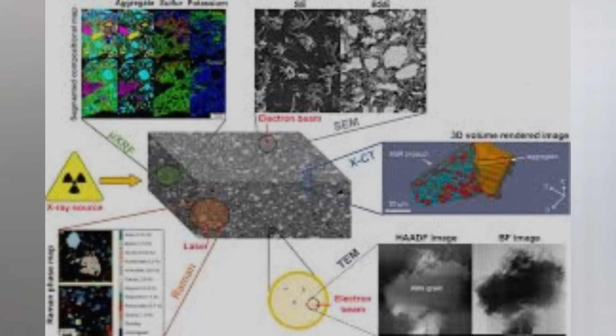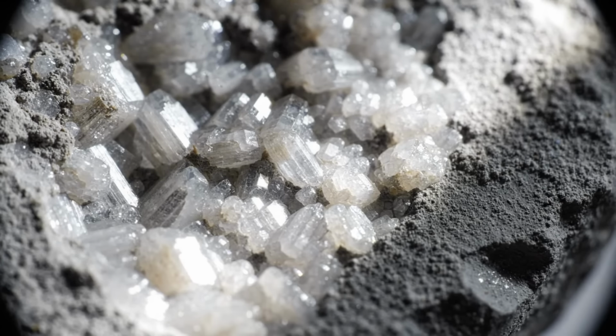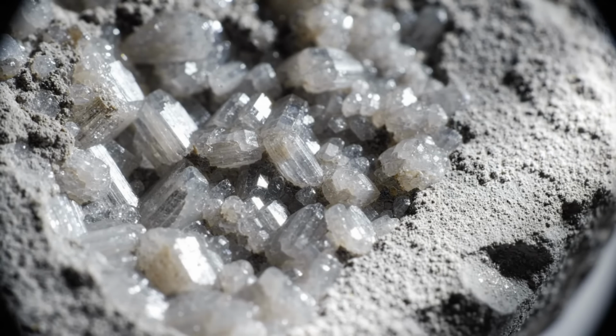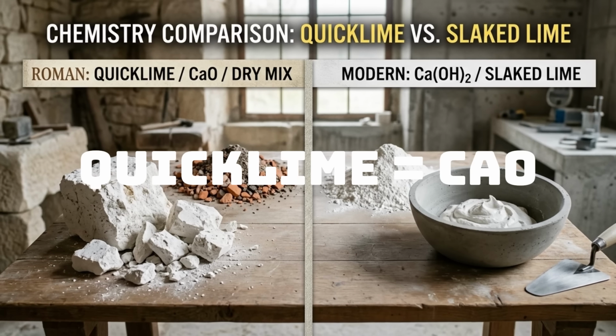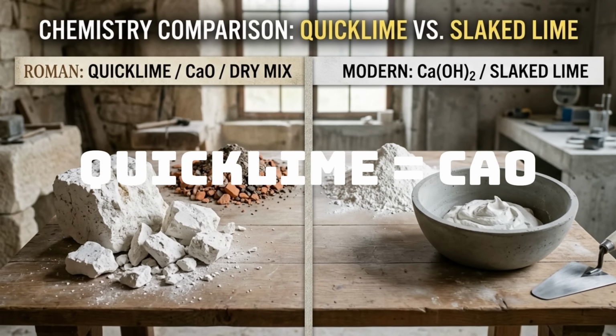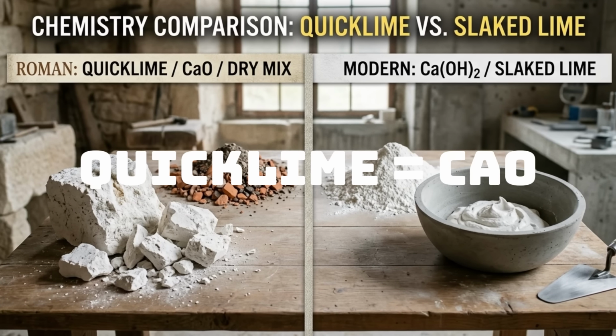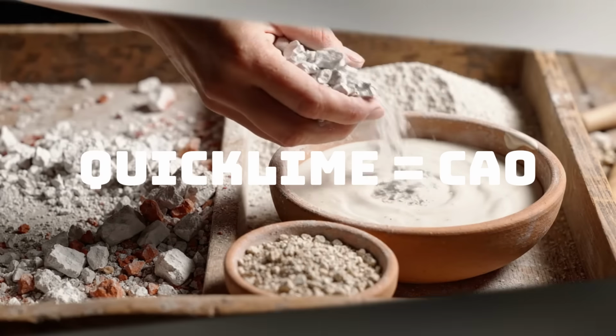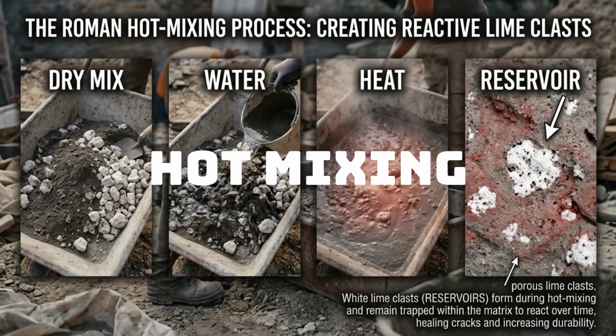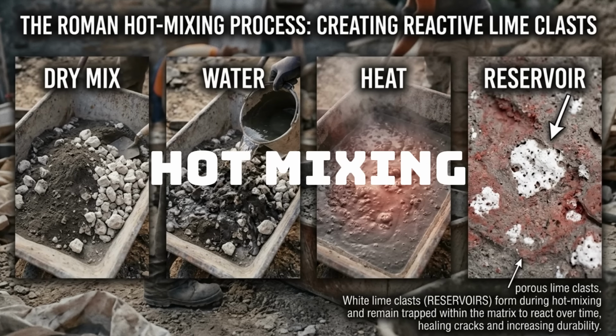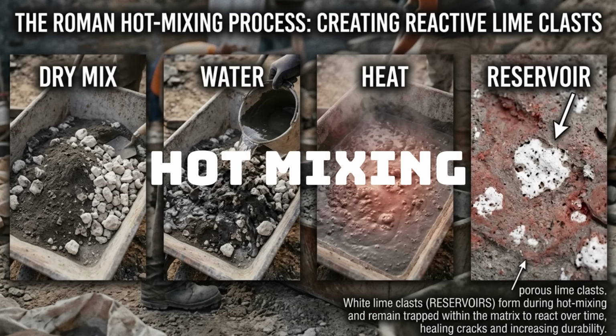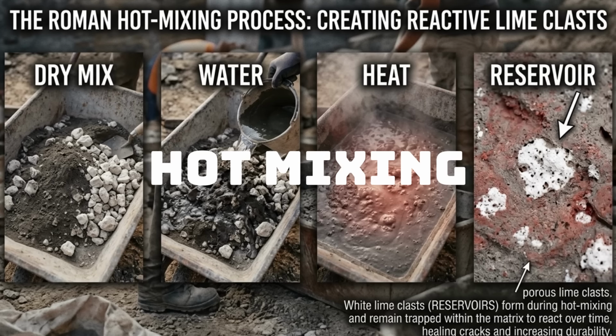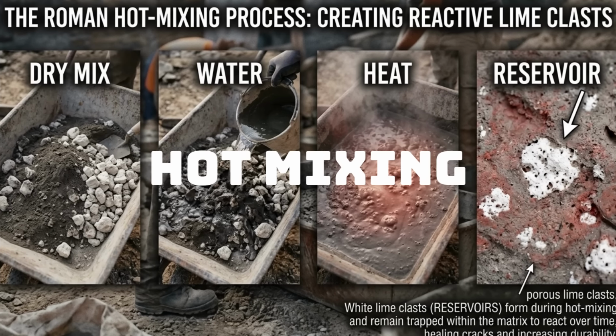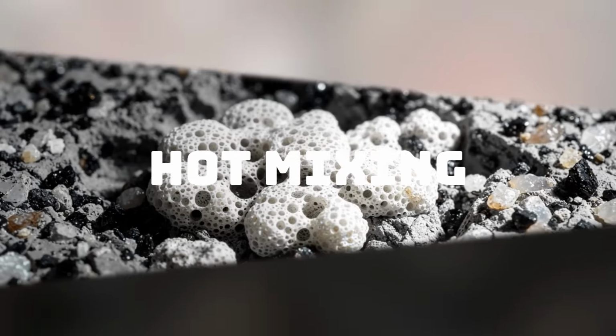His team analyzed the lime clasts using scanning electron microscopy, X-ray diffraction, and Raman imaging. The crystal structures and isotopic signatures told an unambiguous story. The Romans had been using quicklime, the unreacted form of calcium oxide, directly in the dry mix, instead of the slaked calcium hydroxide modern concrete uses. When water hit the dry mixture, the quicklime reacted exothermically. The whole batch heated up. Masic's team called it hot mixing. It trapped the lime as small, brittle, highly porous reservoirs of reactive calcium throughout the matrix.